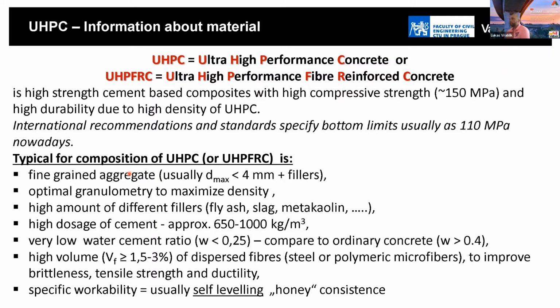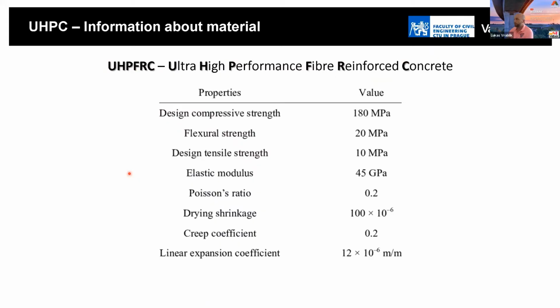Very important is also the question of workability. Usually, we use self-compacting, self-leveling concrete. It is something like honey. You will see a short video of the casting of this concrete, and it is really very close to honey behavior. It is described by the low water cement ratio and also by the fillers, which are responsible for this self-leveling behavior of the UHPC.